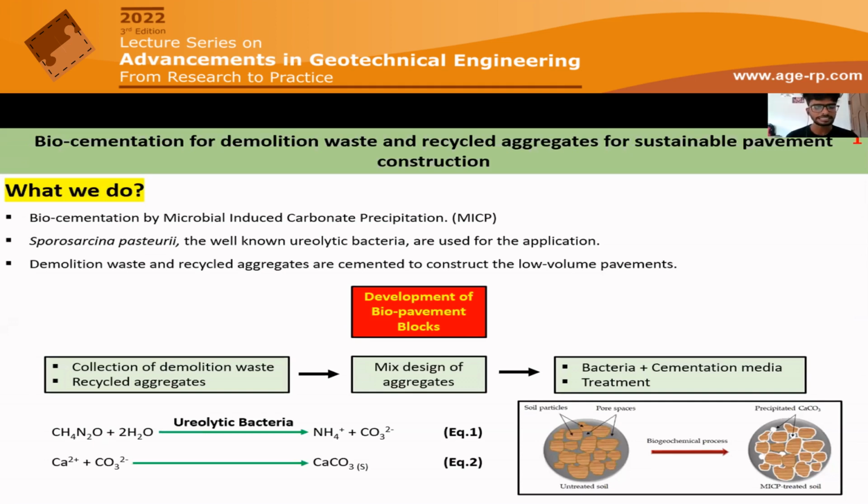For further understanding, we shared the biochemical reactions here, and urea and calcium chloride are the key ingredients of the cementation solution. We are using 1 mole of each for our cementation solution, and the treatment will be continued for certain days.